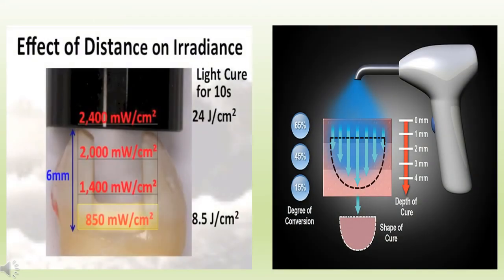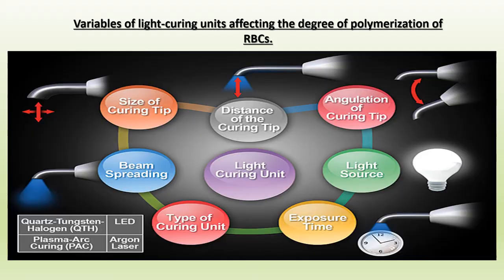The second most important variable we'll be looking at is the distance of the tip of the curing unit from the surface of restoration. The distance between the light curing tip and the composite should ideally be within 3 mm of the composite to be effective. Light absorption and scattering in resin composites reduces the power density and the degree of conversion exponentially with the depth of penetration. Thus, the surface must be irradiated for a longer time to deliver sufficient power density well below the surface.